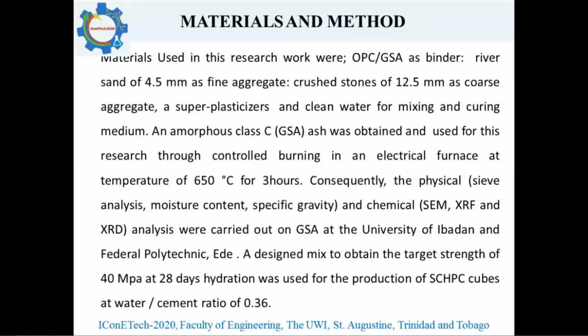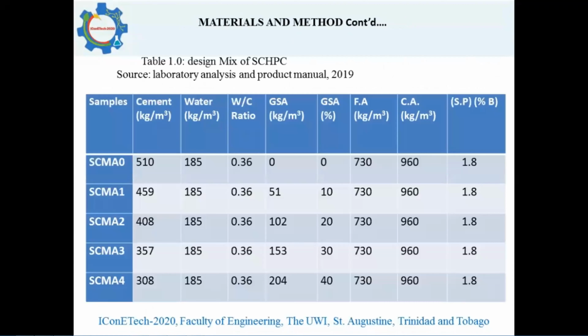Consequently, the physical analysis, the moisture content and specific gravity, and chemical analysis, the scanning electron microscopy, and the XRF and XRD analysis were carried out at the University of Ibadan and Federal Polytechnic in Nigeria. The design, to obtain a target strength of 40 megapascal at 28-day hydration, was used to produce the concrete at a water cement ratio of 0.36. These are the materials used, and the table shows all the materials: the Groundnut Shell Ash, the superplasticizer at 1.8, coarse aggregate at 960, and cement at 510 kilograms per cubic meter.